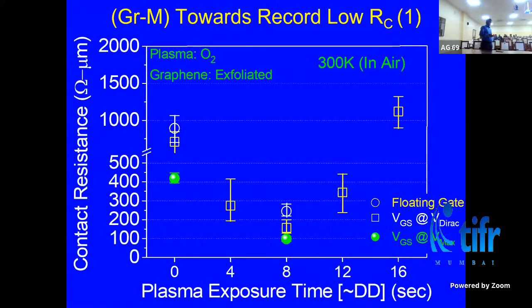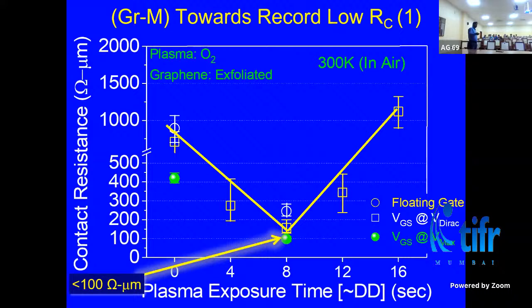So now coming to contact resistance. What we see, we also benchmark with exfoliated graphene, right? Because you see a lot of these numbers reported for exfoliated, and I had shown earlier this 200 ohm-micrometer or 100 ohm-micrometer, all exfoliated, low temperature. That's not the real world; the practical world is CVD, all at room temperature, right? So when you do the exfoliated thing, as a function of this plasma exposure time, which basically varies the defect density, you see an optimum point, right? At the optimum point, you get 100 ohm-micrometer kind of contact resistance, all measured at room temperature, right? If you measure this in vacuum, you get further betterment in the contact resistance.